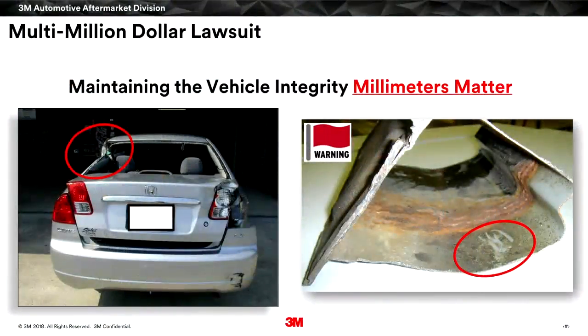Right. Well, the interesting thing here, if you look at the photo on the right, you can see that somebody sectioned a quarter panel at the sail panel, which is common practice and recommended by many OEMs. So they didn't do anything wrong there. They made the weld, and the weld looks okay, but now you see the weld is badly corroded. The one thing to notice here, circled in red, is where there was factory cavity wax on the original panel. Where I scraped it off with my fingernail, you could see where it was, but there's none over the welded area or over the new replacement panel. Right. So they didn't get cavity wax in there.